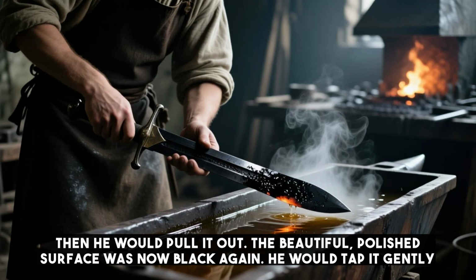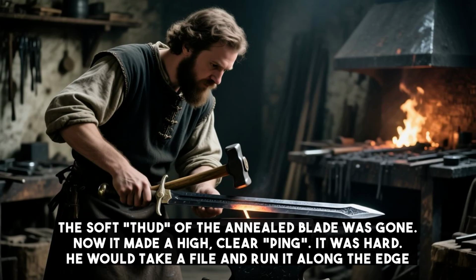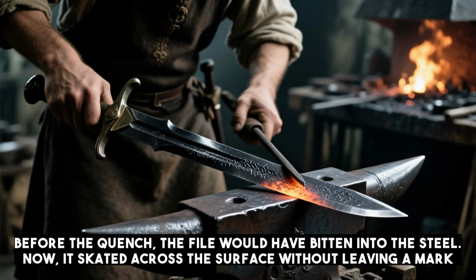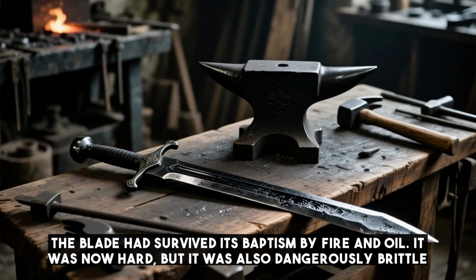Then he would pull it out. The beautiful polished surface was now black again. He would tap it gently. The soft thud of the annealed blade was gone. Now it made a high, clear ping. It was hard. He would take a file and run it along the edge. Before the quench, the file would have bitten into the steel. Now it skated across the surface without leaving a mark. The blade had survived its baptism by fire and oil.